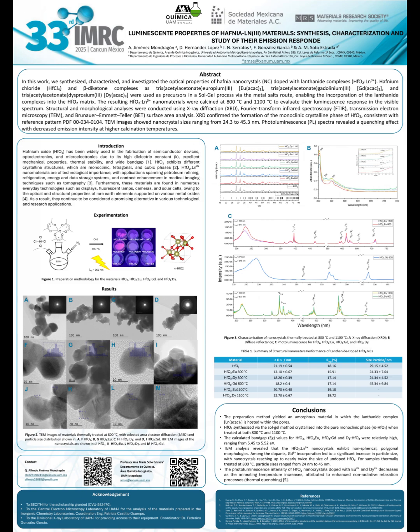Interestingly, similar behavior has been reported in literature, such as by Rosalba et al., who studied zirconia systems and found a linear correlation between temperature and luminescence, influenced by synthesis conditions and structural vacancies.